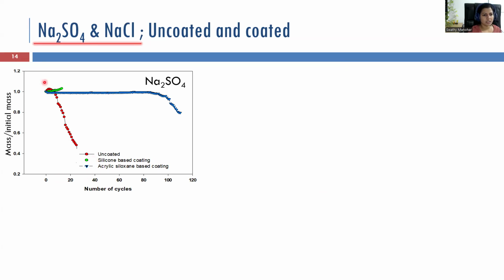You see that the uncoated samples, the red ones, are getting damaged at say 20-22 cycles. But silicone based coating gets damaged even before that. Acrylic based coated samples prevail to be in good condition even after a number of cycles. This is because we see that one particular type of coating happens to be worse than leaving the sample uncoated.